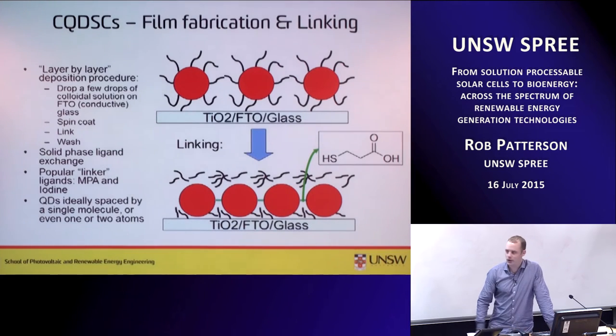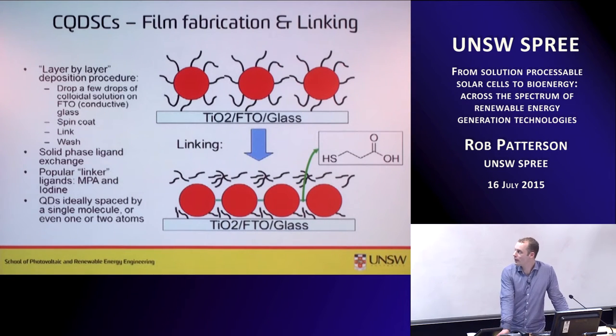Okay, so film fabrication. When we're making these films, it's a little bit different from doing this by sputtering. We spin coat a layer of nanoparticles, and when we spin coat them down, they have their long chain ligands intact. And this is bad for two reasons. We have a very insulating film, because these ligands are very insulating, and they don't stick very well to our substrates.